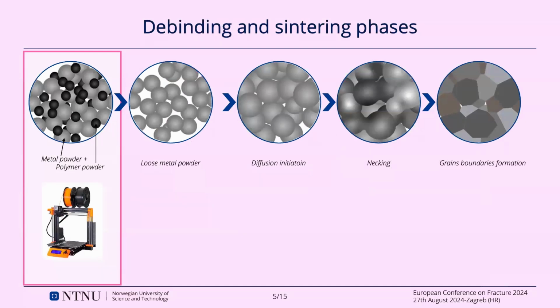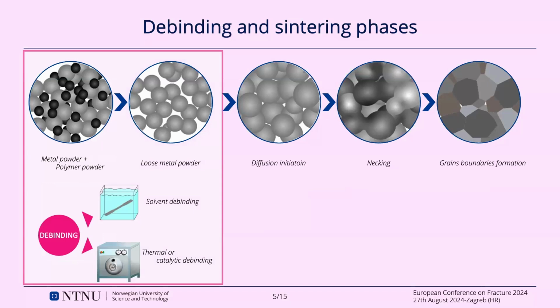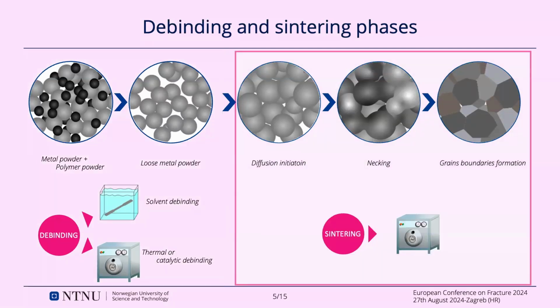So the outcome of the printing phase is just a green part, which has a mixed composition, both metal powder and polymer. Then we have the debinding to remove the binder, and this can be done either with chemicals or with a thermal cycle. And then we have the sintering process, in which the metal powder can diffuse, create necks, bonds, and then the grain boundary is set in.